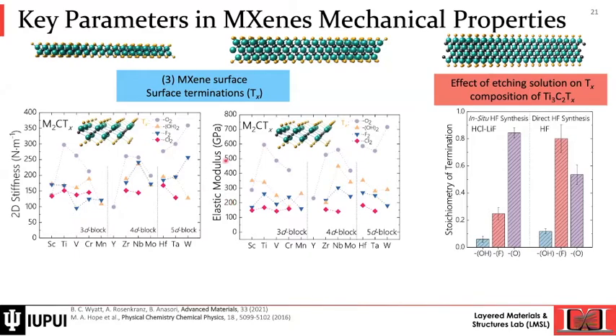Now, you might say, well, usually we are using the hydrofluoric acid route or the LiCl hydrochloric acid and lithium fluoride routes, so we don't have control over surface termination. I want to emphasize that we can control the composition, the ratio of surface termination, just by playing with what type of etching route we go. This is from a study that was published in 2016 that showed if we use hydrochloric acid with lithium fluoride, which has a lower concentration of HF, we'll have more oxygen on the surface, versus when we use a higher concentration of just HF, hydrofluoric acid, and we'll have more fluorine and less oxygen. So just by changing the etching solution composition, we can tune to some degree the surface termination.